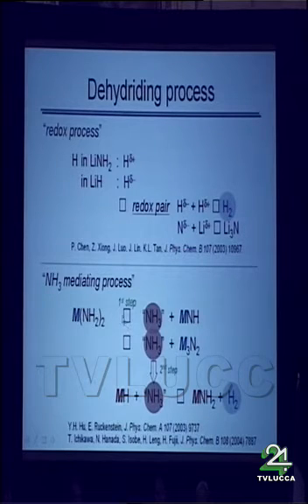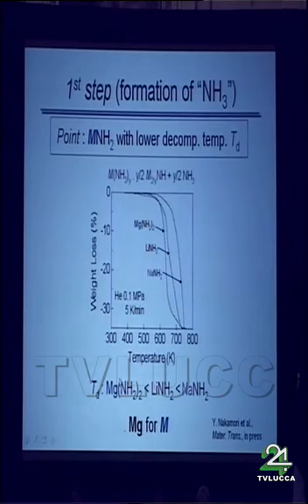In this process, in the first step, the amide changes into the imide or sometimes nitride to form the ammonia-like phase. And as a second step, the metal hydride reacts with this ammonia-like phase to form the actual hydrogen. This proposal was made by Dr. Hu and Dr. Ichikawa's paper. If we take this process, we can select or optimize this blue M and red M independently. For example, as a first step, the point is to find the metal amide with, let's say, blue M here, with lower decomposition temperature to easily form the ammonia-like phase.